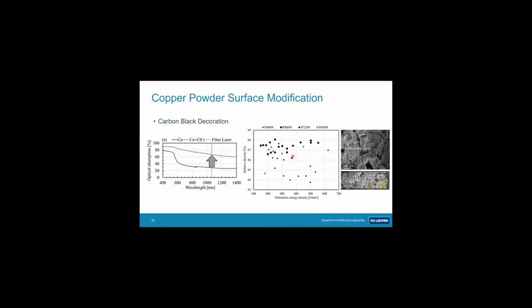So whatever you do to your powder particle, you have to make sure that there is still an effect of that in the melt pool itself. And so it seemed to work for nickel, it seemed to work for what we showed before for oxygen. And that is basically because copper and nickel form a solid solution also in the liquid. For the oxygen, copper oxides are fairly well wetted by liquid copper. So we think that they could still play their role from the moment they were sucked in, because there is a suction effect, as I will show later.